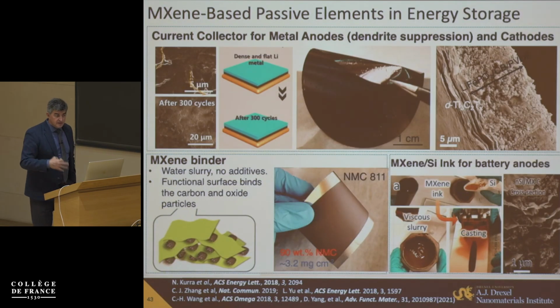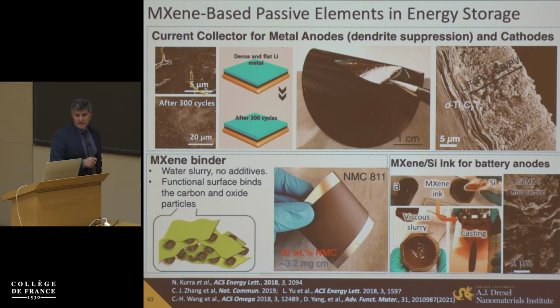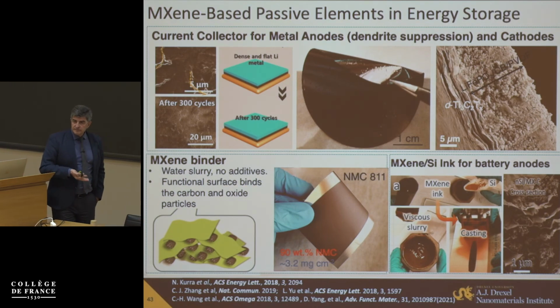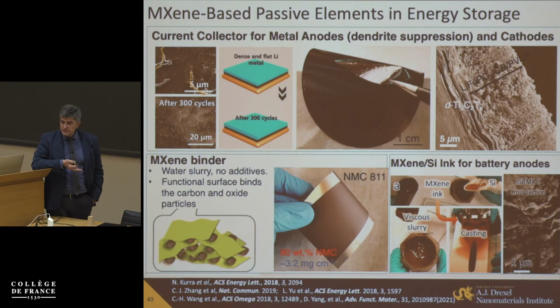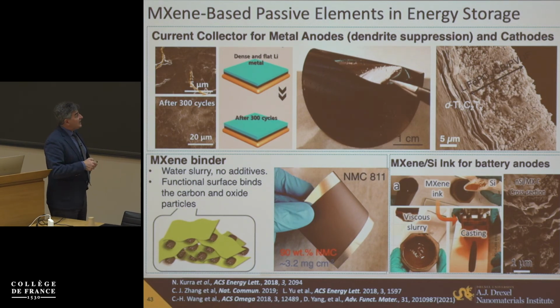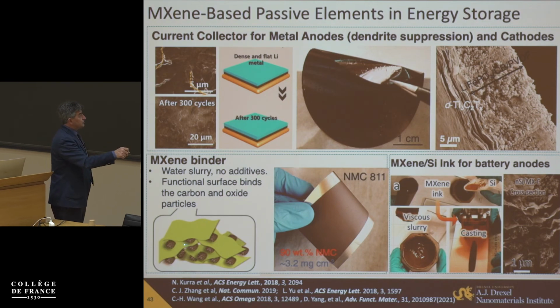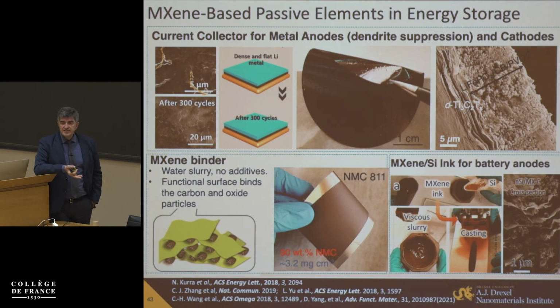Now, going back to what I mentioned at the beginning, we have materials with high conductivity and high mechanical properties. Hydrophilic, oxygen-terminated surfaces which are oxide-like. And actually, they can act as binders for silicon, and even for porous carbon, because you may think of, say, activated carbon as a highly conducting material.